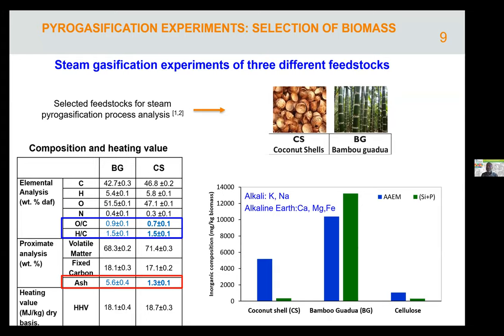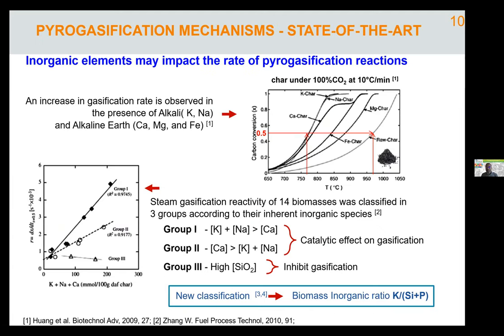The selection has to be made in regard of the objective. If the objective is making biochar, for instance, then it's gonna be the opposite. I'm gonna use bamboo because the ash content should be much higher. This is what people do, the preliminary assessment for the selection of the stream. And the literature says also that you can predict the efficiency by selecting the metal ratio. They are classified in the literature in three groups. Group one, where the alkali are much higher than the alkaline earth, group two, the opposite, and group three, where the inhibitors are much higher.